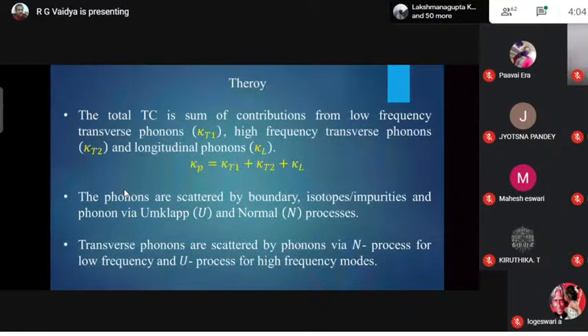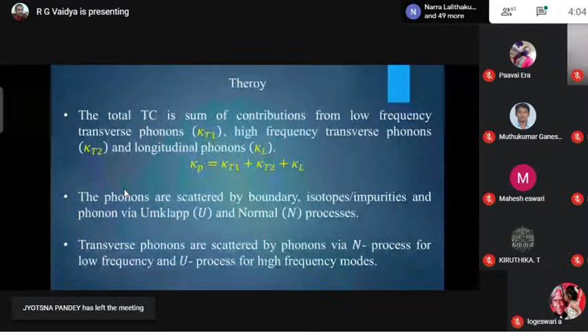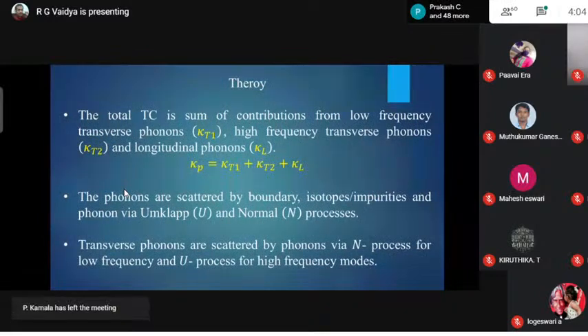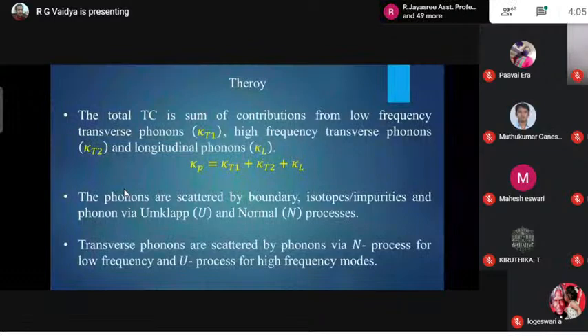In theory, we have employed Boltzmann transport formalism in which the Holland model has been used. The Holland model gives the opportunity to calculate the contribution from low frequency transverse phonons, high frequency transverse phonons, and longitudinal phonon contributions to the total lattice thermal conductivity.